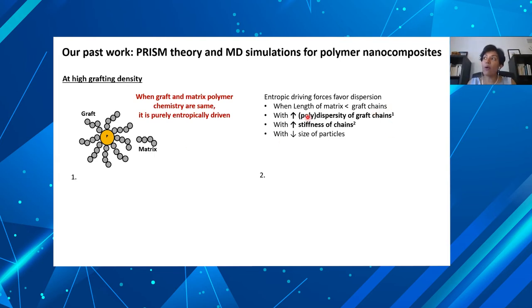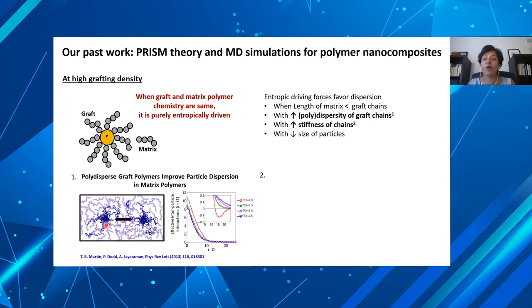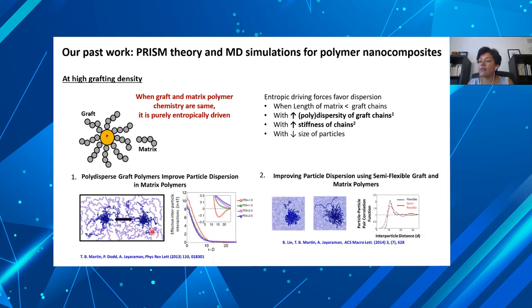And we found that we can also favor dispersion and tune the entropy towards that by increasing polydispersity or dispersity of graft chain molecular weights in a matrix that is not so polydispersed, not so dispersed in molecular weight. And we showed that using calculations with PRISM theory and MD simulations, and that's shown here, that two particles' effective interactions in the matrix goes from being attractive at the monodisperse level to becoming purely repulsive as you dial in dispersity in molecular weights. And that again goes back to some terms that are increasing that mixing entropy gain, driving it to dispersion.